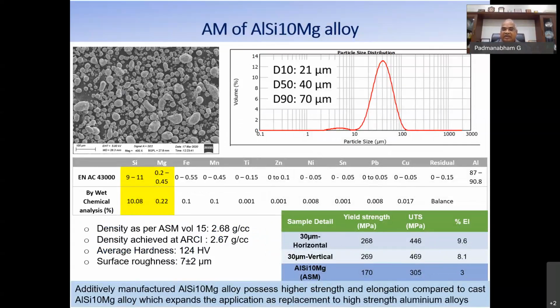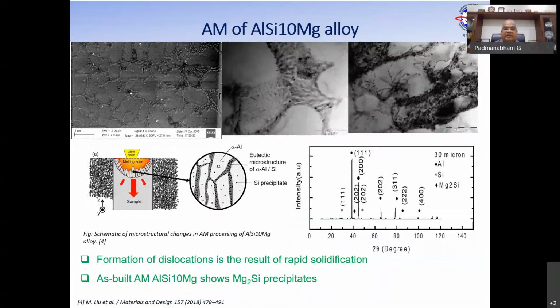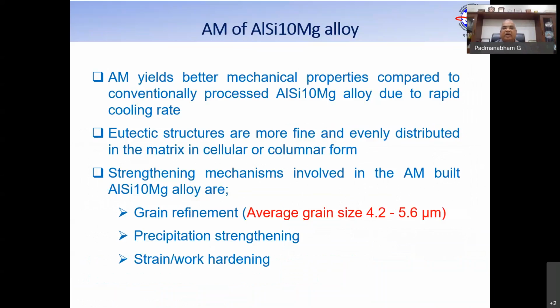The last row, ASM, is the standard properties, in terms of yield strength, ultimate strength, as well as elongation. All the properties have improved in the case of additive manufacturing. And all this is because of the formation of dislocations, which you can see in the microstructure, because of the rapid solidification process. Also, in the as-built condition itself, we have Mg2Si precipitates, which strengthen the material. So again, the process gives you an advantage. That's what I have said already.